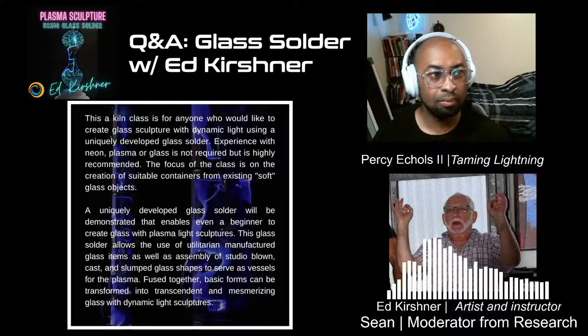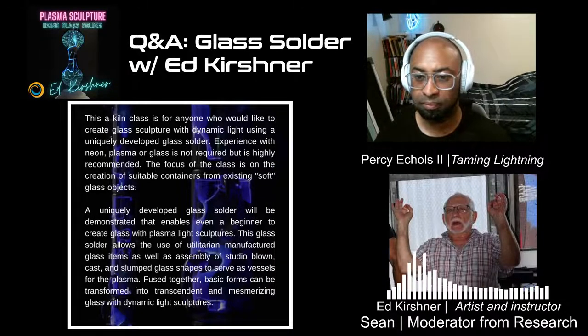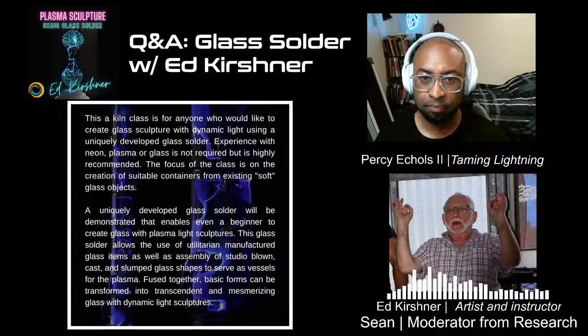For this particular class, I find that the solder works best with studio blown glass. They can be production pieces, but basically studio blown glass would be best. Manufactured glass is okay, but much more difficult and has more failure rates, because most manufactured glass is somewhat harder. It's the matching of the electrodes, the neon electrodes that we have to use, and other aspects, that make it better to use studio glass. That's been my experience.